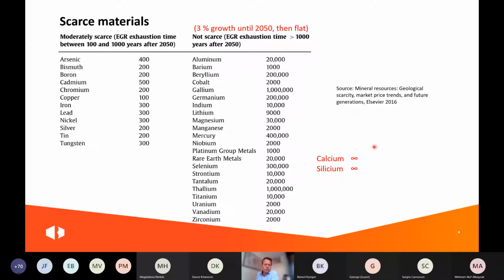Here you see also aluminium. Aluminium is not mentioned as scarce, 20,000 years available, but that's based on the current production of aluminium and a growth assumption of 3%. But if we start using aluminium as a raw material for cement production, and we will discuss that later on for one type of alternative binder, then this 20,000 years, of course, will be strongly reduced. So that's important to take into account.